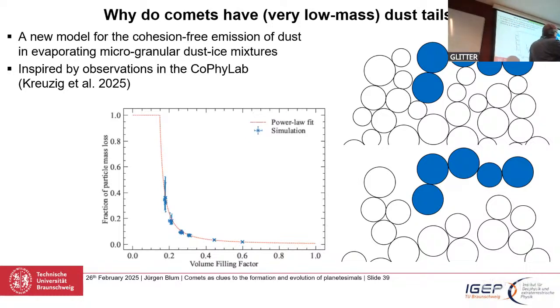So imagine we have a size distribution of ices. Everything is ice, regardless of whether it's blue or not. And the top 1,000 layers or so are more or less isothermal. We calculated the optical absorption of the light, and the first millimeter or so is isothermal. So this is all the same temperature. And of course, if it's all the same temperature, the small ice particles like this or that or this or that, they evaporate faster than the large ones. So they go away. And this is the lower picture here.